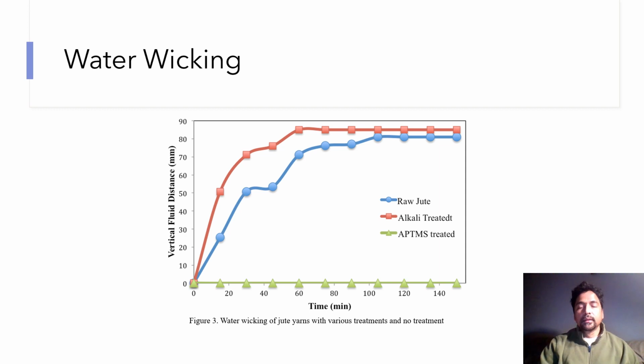Getting into the results, I wanted to present here the effect of alkali treatment and the silane treatment, which is APTMS treated silane, on the hydrophobic nature of the jute fabric. Now, as you can see, the raw jute can absorb water in the water wicking experiment, where it can absorb up to 80 millimeters of long absorption.